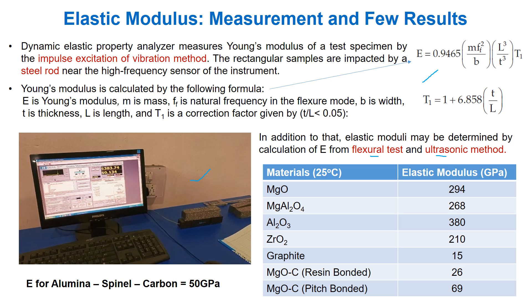A recent development indicates alumino-spinel carbon with a 50 GPa elastic modulus. While comparing the E value for different grade magnesia carbon bricks with virgin materials MgO and graphite, we can see the existence of a large difference attributed to porosity and different quality of binder. One can predict why pitch-bonded magnesia carbon refractory has relatively low thermal shock resistance compared to resin-bonded magnesia carbon, because thermal stress is the product of alpha and E, and E is lower in one case and higher in the other.